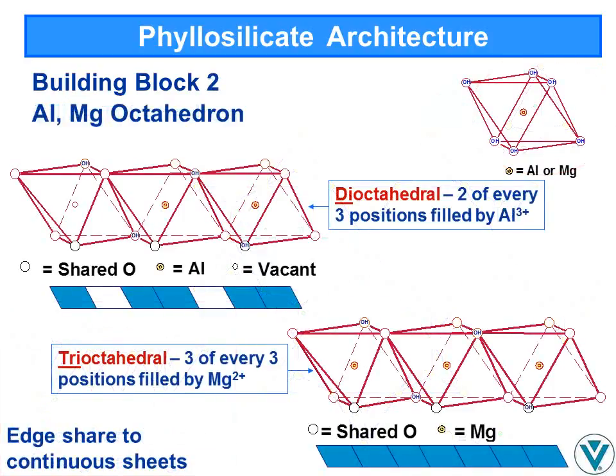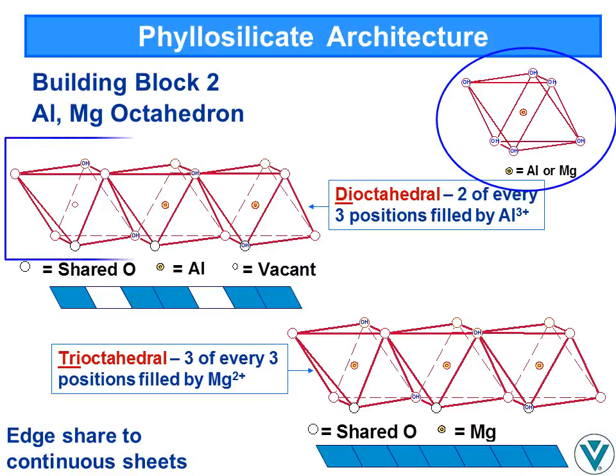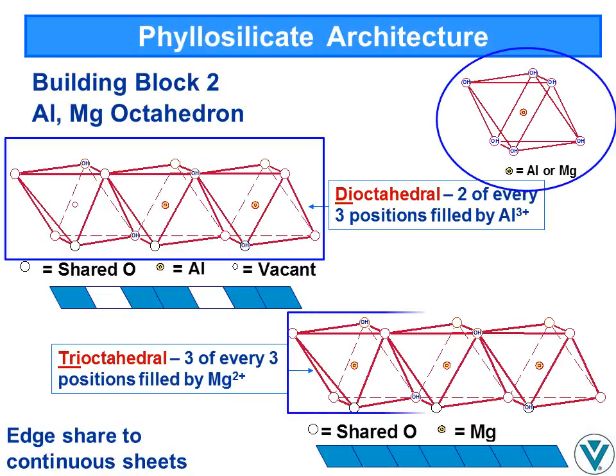The other monomer is the octahedron formed by aluminum hydroxide or magnesium hydroxide. The phyllosilicates contain a continuous octahedral layer with the joined octahedra tilted on a triangular side. When the predominant octahedral cation is Al3+, charge balancing within the clay lattice requires that only two of every three octahedral positions be filled, and the clay is described as dioctahedral. If Mg2+ predominates, all octahedral positions must be filled for charge balancing, and the clay is called trioctahedral.